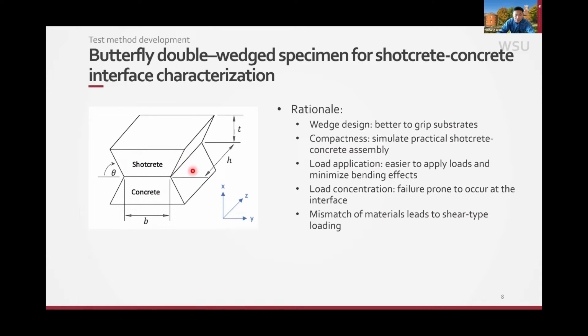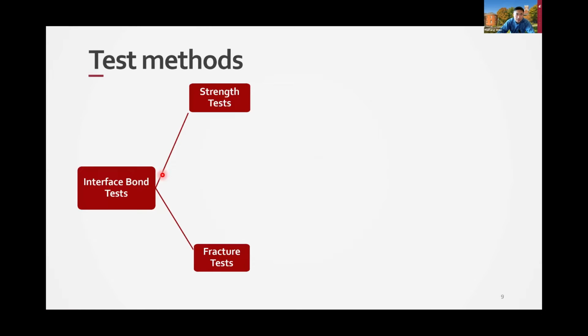It also has a relatively small size. You can do it in the lab, and you can apply the load while minimizing the bending. For a tension test, bending is a concern. Sometimes you don't know whether the failure is due to the tension or due to the bending. By doing this method, there's the potential to minimize the bending, and because of the shape, we can almost guarantee that the failure will be at the interface or close to the interface. So those are some advantages of using this sample design.